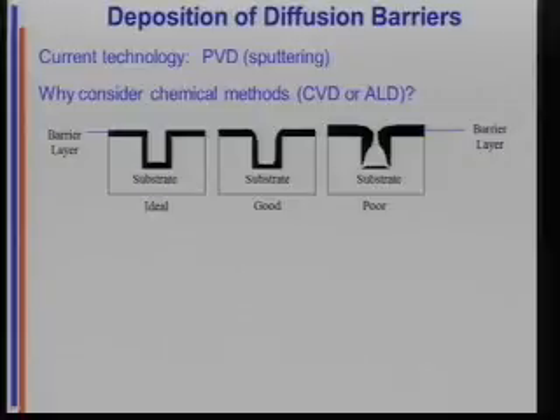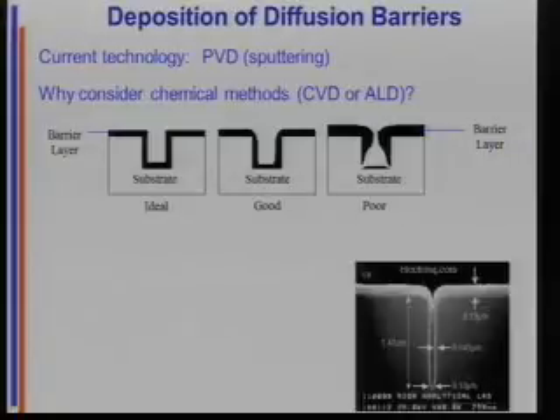The side wall is not going to be covered well. You kind of block it. This is called a pinch-off site. And there are going to be holes down the side wall. In fact, this is an SEM image, not ours, of sputtered material on a high aspect ratio feature. You can see this light gray stuff is the sputtered material. So it's thick here, and it's not very well covered down the sidewalls.